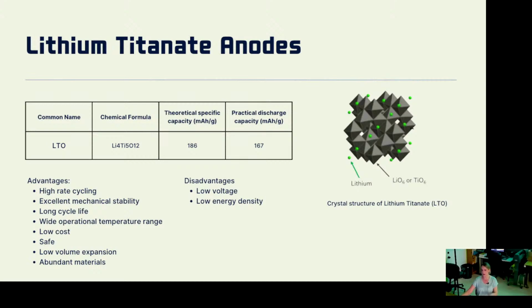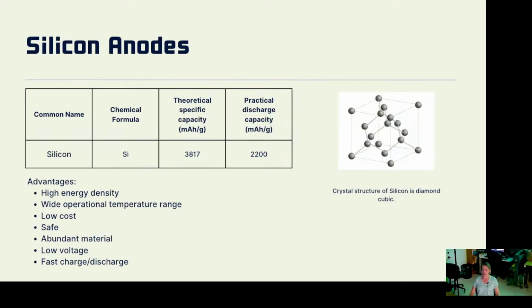So lithium titanate is an awesome material, but it does have low voltage and low energy density. It's usually used in stationary storage applications, not so much in electric vehicles. Silicon anodes are considered a next-gen battery material. You can see the energy density here is an order of magnitude higher than graphite. Crazy capacity, crazy energy density for this.